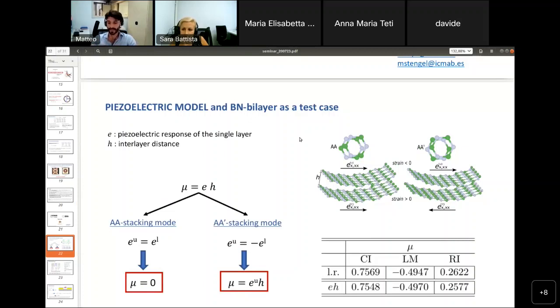One is the so-called AA, where the two layers are just one above the other, and they have the same orientation. And then consider the AA' stack, where we have again two equal boron nitride layers, but rotated with respect to each other by pi. In such a case, if we consider the two layers distant enough to be considered non-interacting, the flexoelectric effect is exactly given by the piezoelectric response of the single layer. In particular, one can show that the quantity mu that we defined in the presentation, that is the in-plane flexoelectric response of the two-dimensional material, can be exactly written through the in-plane piezoelectric response of the material and the interlayer distance of the layers.